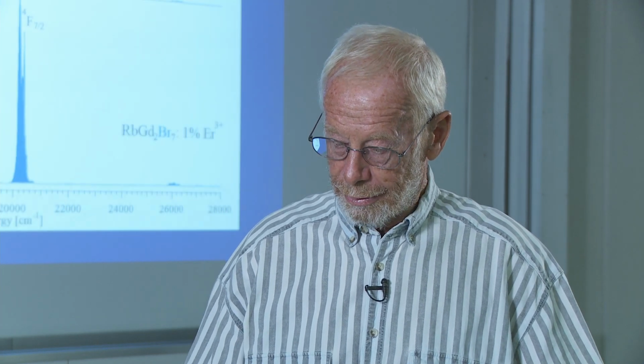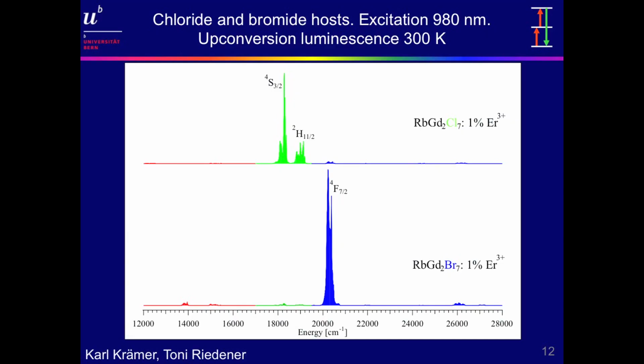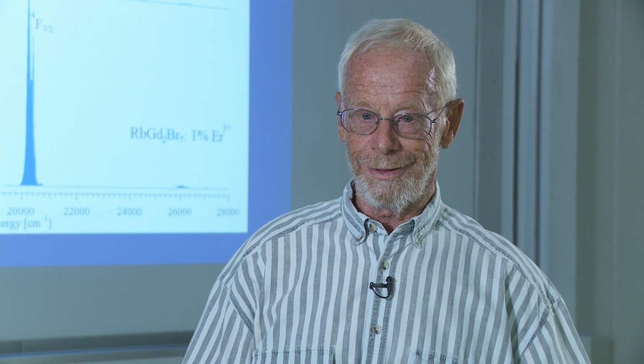We put it in chloride and bromide lattices, here 2 isostructural lattices. The upper trace is a chloride, the lower a bromide, and the upper one is an almost pure green luminescence, whereas the bromide is an almost pure blue luminescence. So we had an immediate effect.